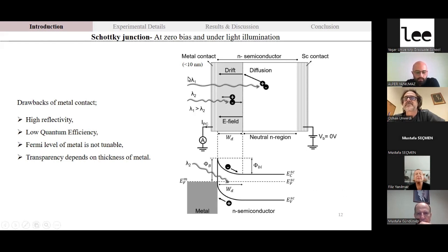But we know that when light strikes the junction, electron hole pairs are generated, depending on the energy of the light. Here, generally, metal contacts less than 10 nanometers are used, and the drawbacks of the metal contact are the high reflectivity, by the way, the low quantum efficiency, and the most important thing, the Fermi level of the metal is not tunable. This is the highest drawback of this structure, and the transparency depends on the thickness of the metal.